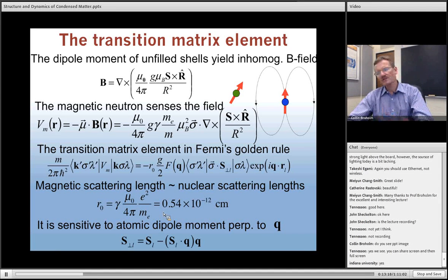And we'll also see Bragg scattering that has to do with the orientation of the magnetic dipole moments of the electrons that are presenting an unpaired, that are in the partially filled shells. So these partially filled shells will generate magnetic dipole moments, which generate fields, which give rise to scattering.